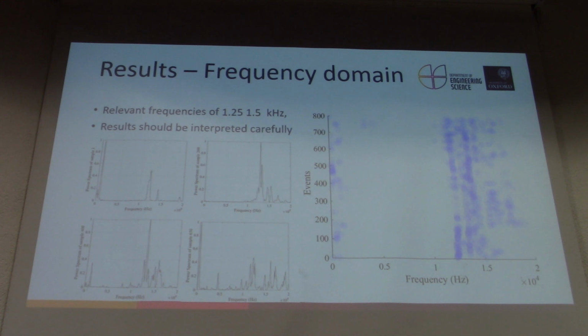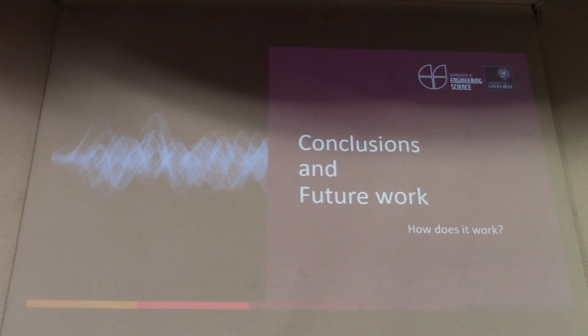Looking at the frequencies with care, we found that some main frequencies are in the order of 1.25, 1.5 kilohertz. But these results should be taken with care, because these main frequencies are not necessarily intrinsically related to the fracture of the fibers, but could be the result of the system, fibers plus testing rig.